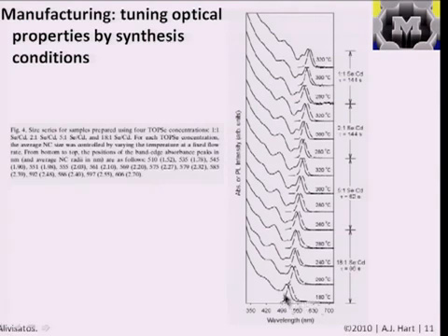And here they've just plotted the absorption and emission spectra of a whole bunch of cadmium selenide quantum dots that are prepared using different synthesis temperatures. So for now, we can just imagine having a beaker or a vat with the right chemicals in which the dots grow, and that being heated at a certain temperature for a certain time. And by changing the temperature, the ratio of the particular precursors, and the time at which you heat it, they've backed out this beautiful trend in the spectra and, in effect, in the size and the size distribution of the particles.